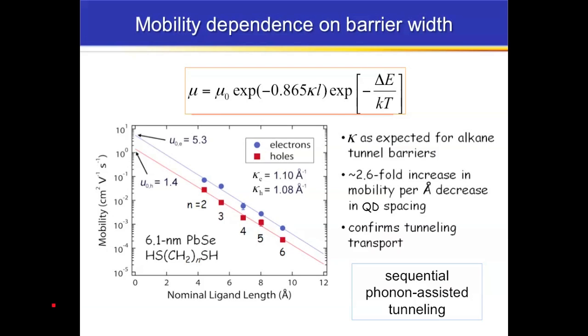Down here is basically what we call the nominal ligand length. This is effectively the distance we think that the quantum dots are separated by. And this is exactly what you would expect for tunnel type transport between quantum dots. We can fit it to an expression and extract out the tunnel decay parameter, the wave function decay parameter. And everything fits for an alkane kind of tunnel barrier.